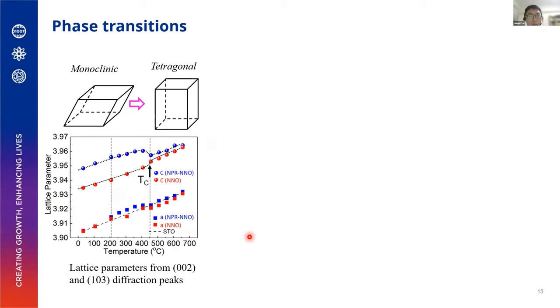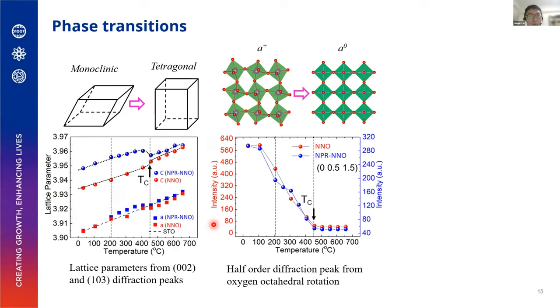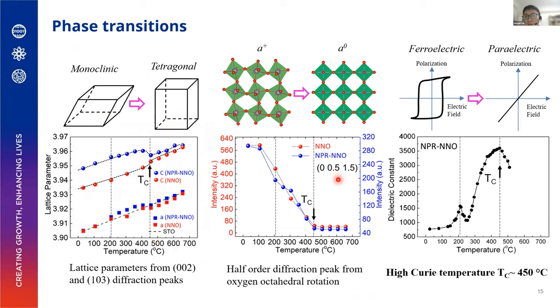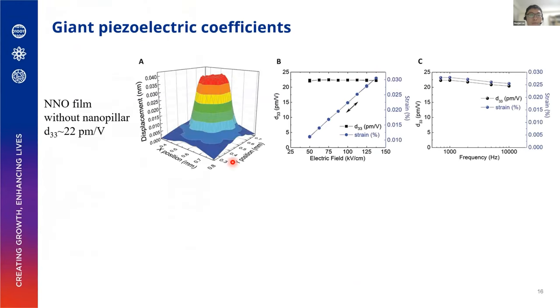And we also did a temperature-dependent study to determine the Curie temperature by monitoring the lattice parameters as a function of temperature, and also the octahedral tilt. So this also agrees with the dielectric constant testing. So we are able to maintain the high Curie temperature of the system as we don't introduce a lot of dopants. And then with this film, we measure the piezoelectric coefficient using the laser scanning vibrometer.